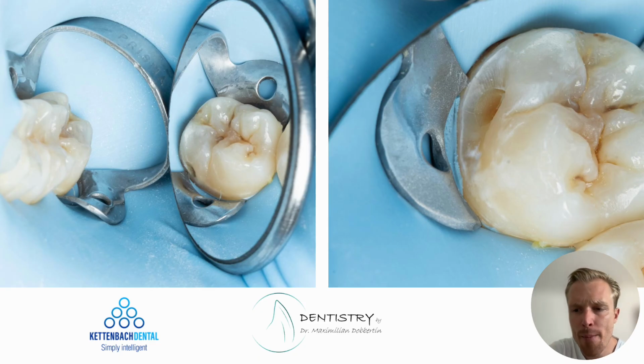And as you can see here, back to adult teeth, also in cavities that are a little bit discolorated, bulk fill composites such as the Visalys Bulk Fill may work quite in an aesthetically high demanding way. So as we can see here, this is some kind of a class 5 lesion, a buccal lesion. And isolating this properly with rubber dam and a clamp, we can then assure to place the bulk fill composite restoration most effectively and most efficiently without any hazards of leakages.